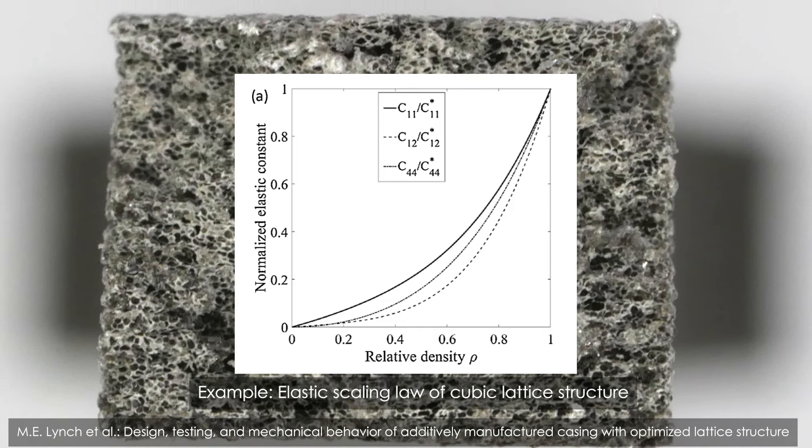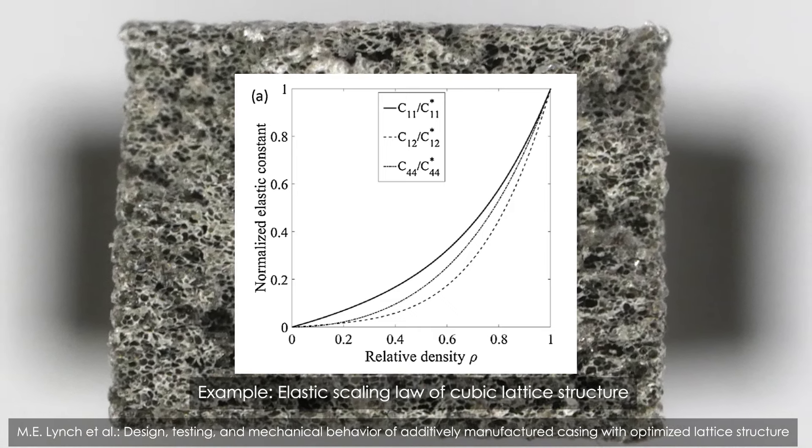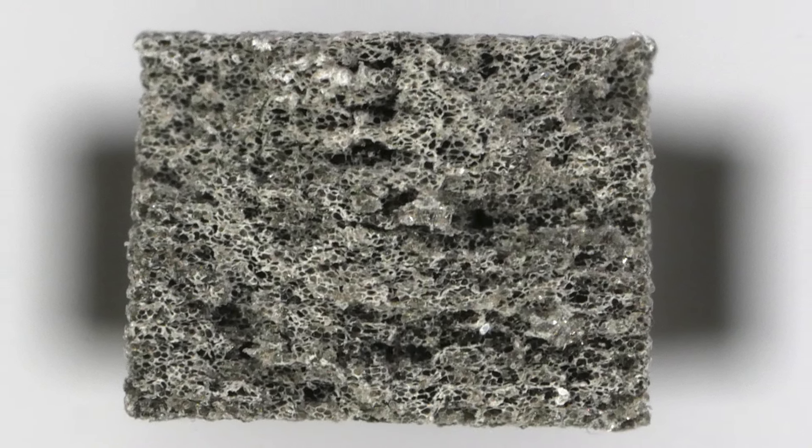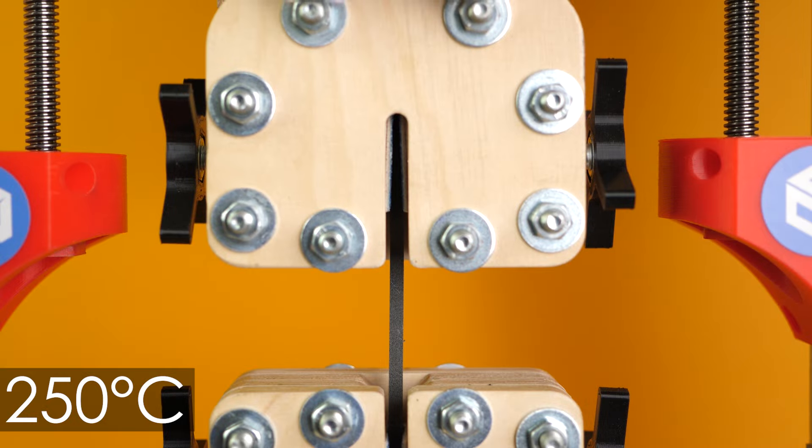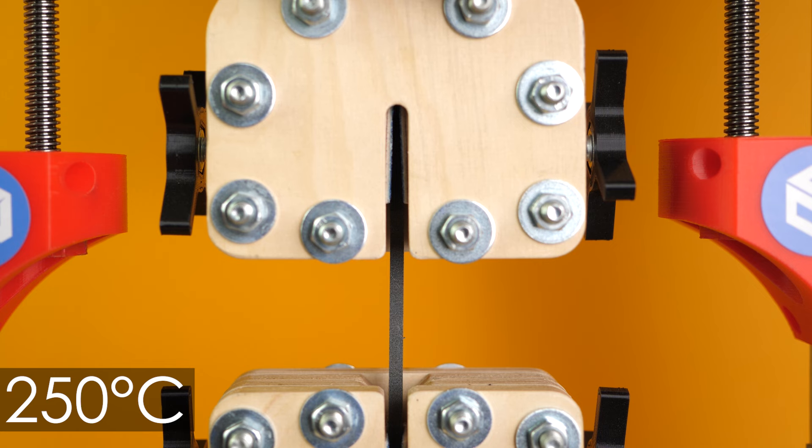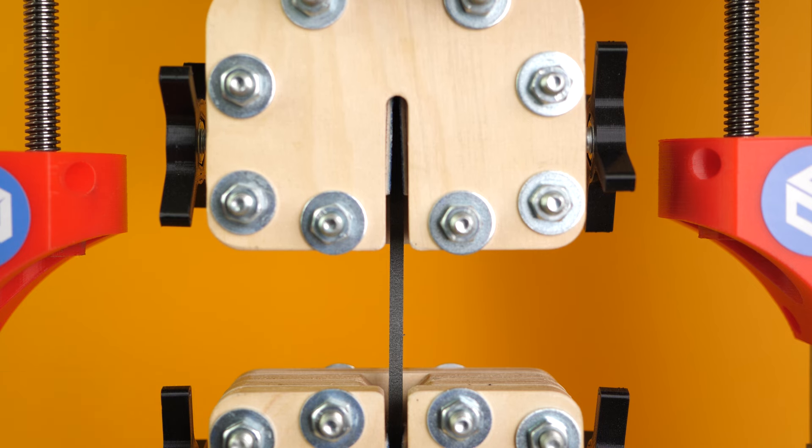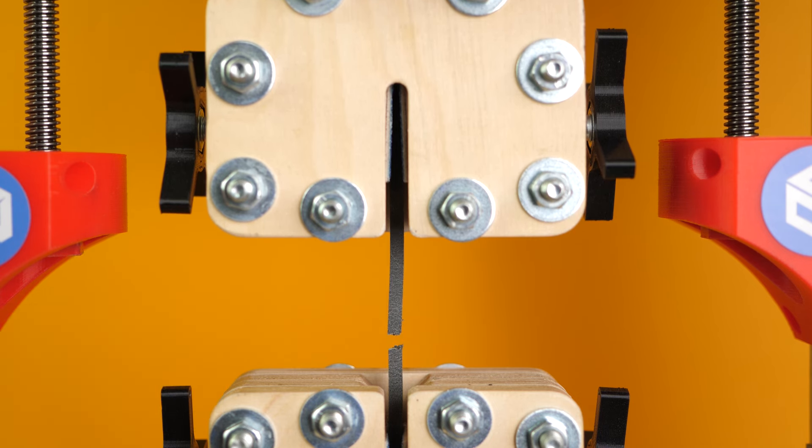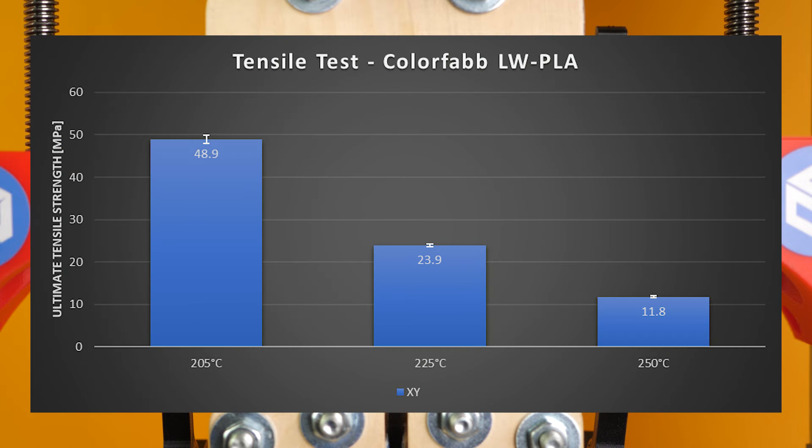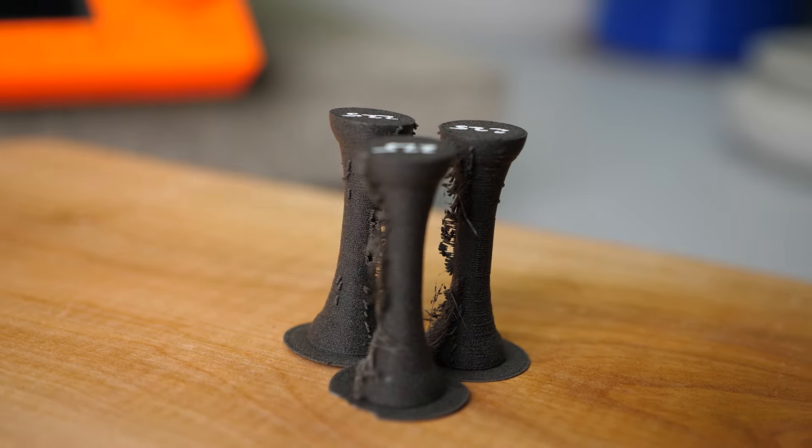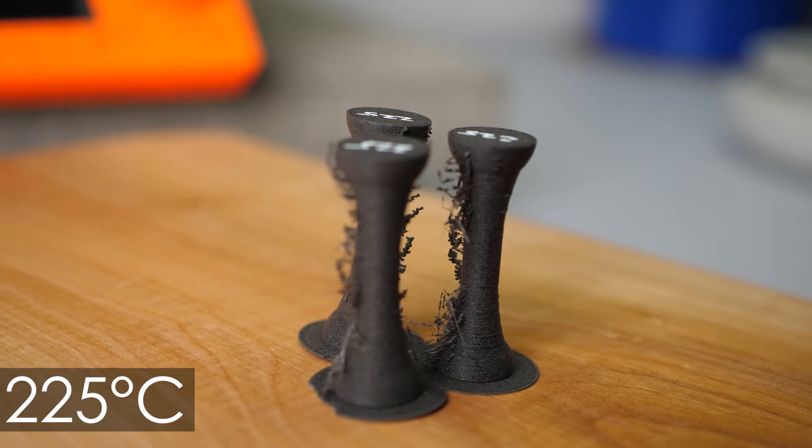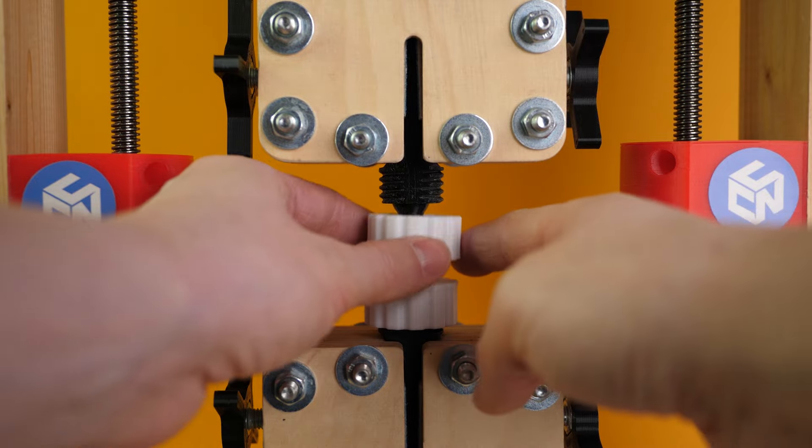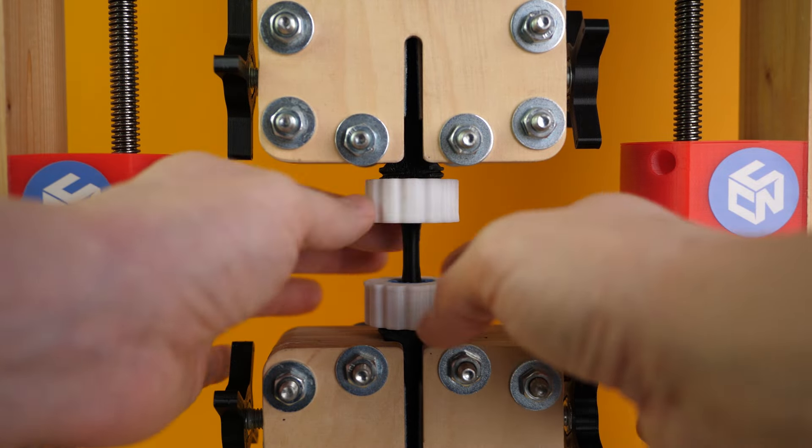The degree of nonlinearity is dependent on the type of lattice or porosity you have and differs in severity. The parts printed at 250 degrees Celsius were able to bear a quarter of the reference and snapped at only 12MPa but not in a brittle way and they seemed to yield considerably before failure.